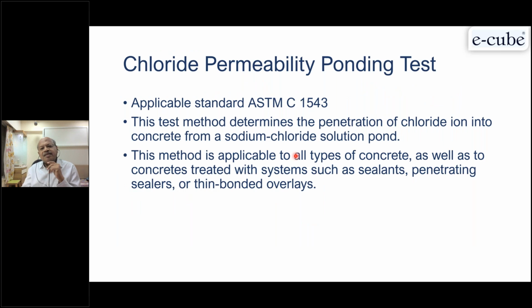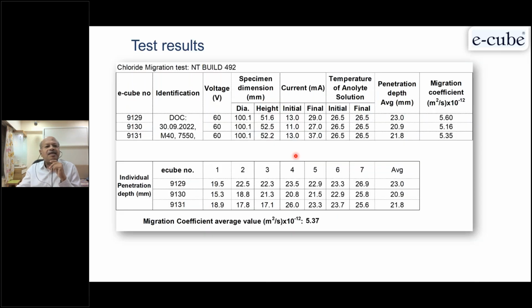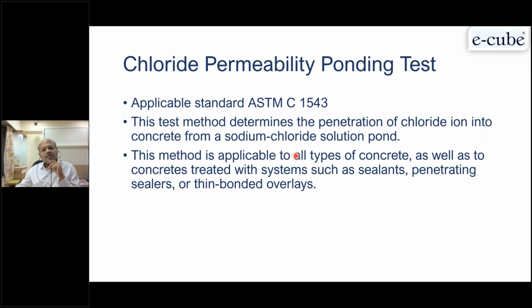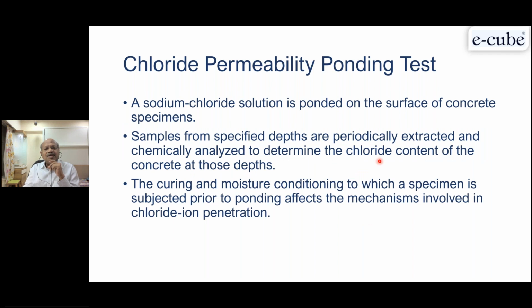Now this is a real life test. It means you are putting in the actual chlorides, ponding the specimen and keeping it for say 35 to 90 days. But it takes a lot of time. Other tests are done within 1 or 2 days after 28 days are over, but this takes at least 90 days. So you take the specimen, put in your sodium chloride solution, and keep it for at least 90 days. And then you remove the specimen from the sodium chloride solution, and then you grind the specimen with depth. You take the first 5 mm, then the next 5 mm, then the next 5 mm, and then you analyze chemically for chloride content, to see how the chlorides have penetrated from the surface to the depth under normal ambient conditions.